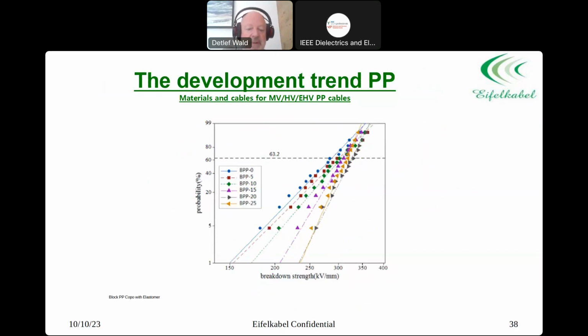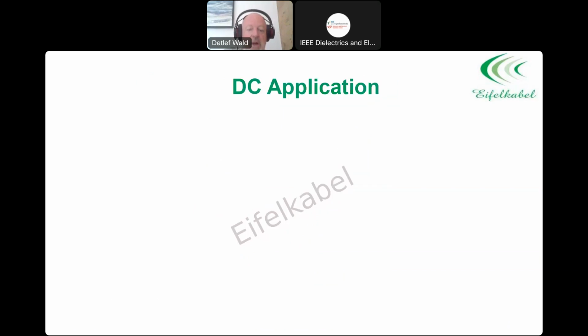And again, breakdown test. Here again, polypropylene with mixtures. You can see the blue one in the middle here, or better say over here, and the improvement. So polypropylene with only 10% of the second polymer gives you actually the best advantage in breakdown strength. And here it was a PP copolymer with an elastomer. That was a little bit about AC application.